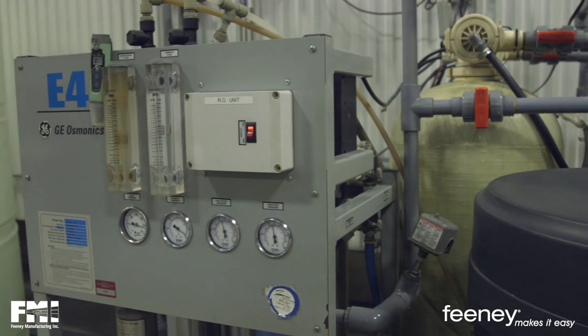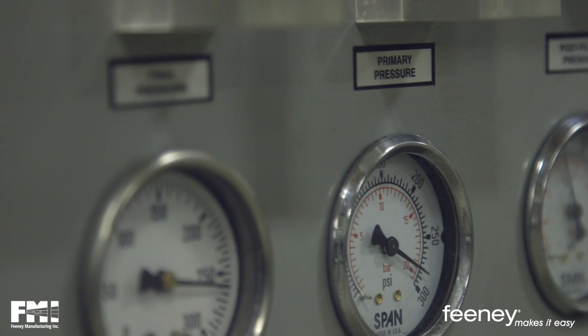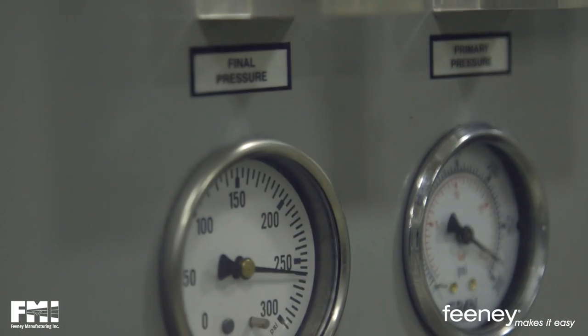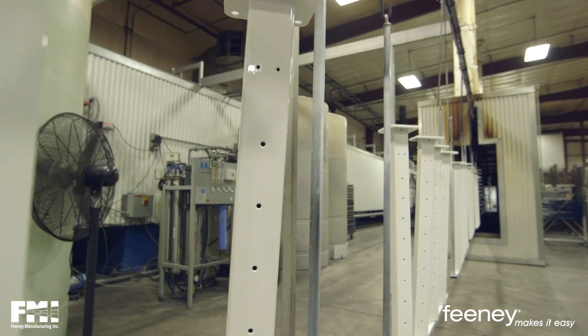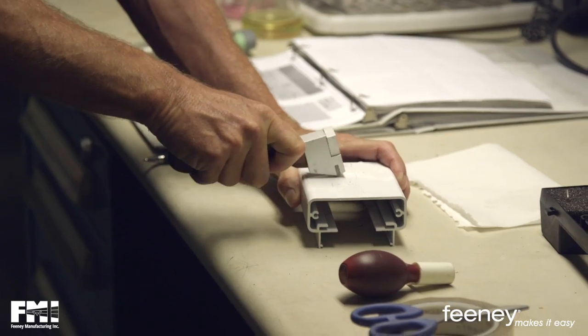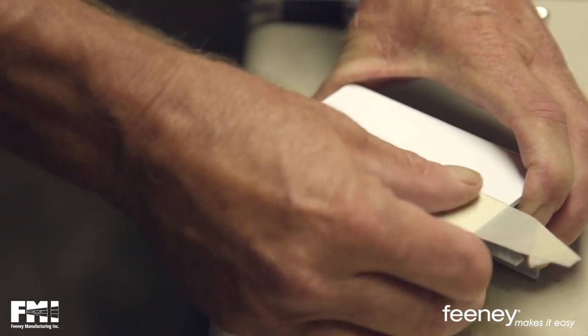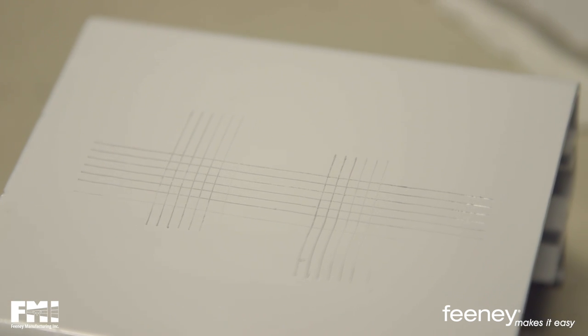Our engineers carry out detailed temperature analyses to determine the ideal firing and curing times for each Design Rail railing. A sample railing piece is cataloged each day from all colors used during that day's production. The sample is then subjected to a variety of tests, including the scratch test and MEK rub test. These tests confirm the effectiveness of the powder's adhesion to product surfaces.